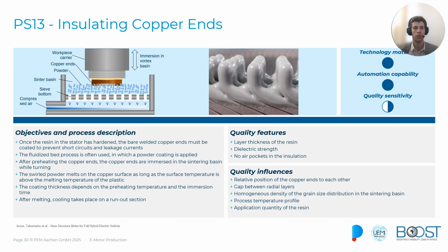Quality features of this process are the layer thickness of the resin, the dielectric strength of the insulation, and to avoid air pockets in the insulation during this process.